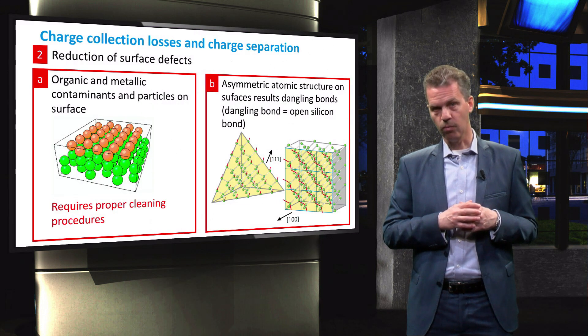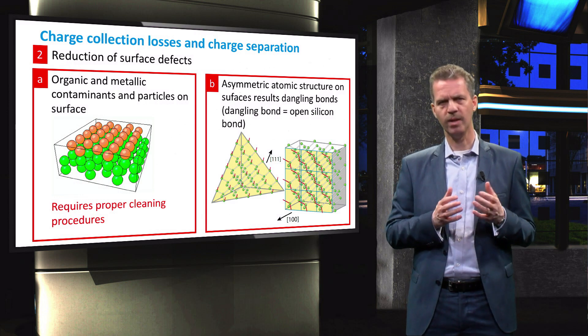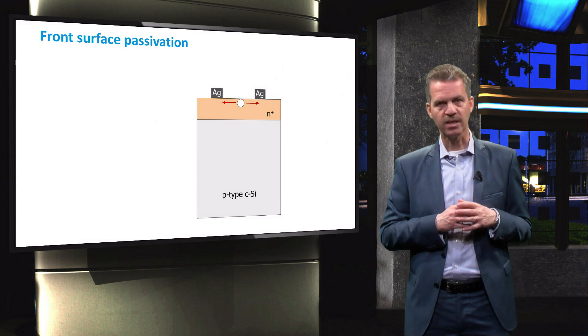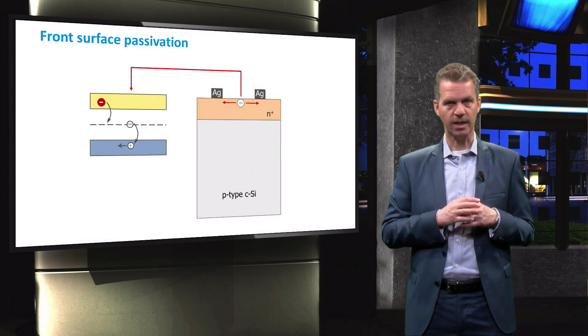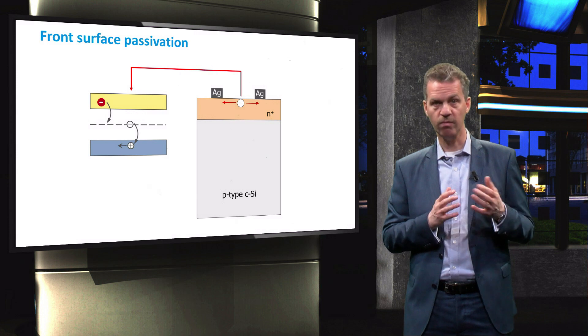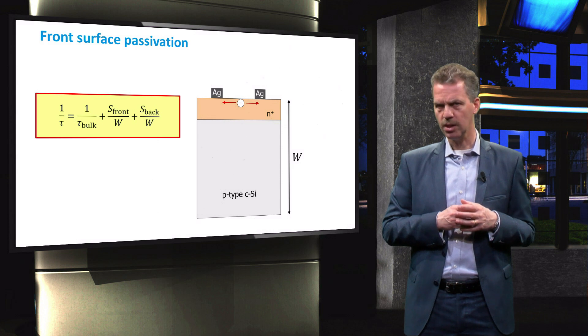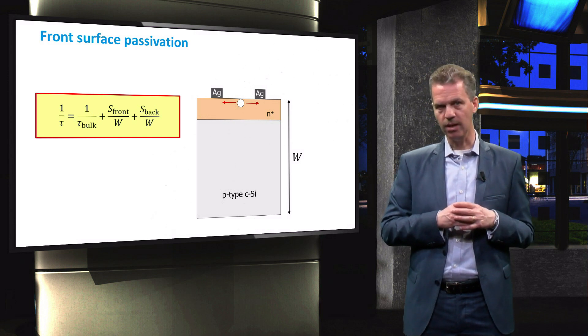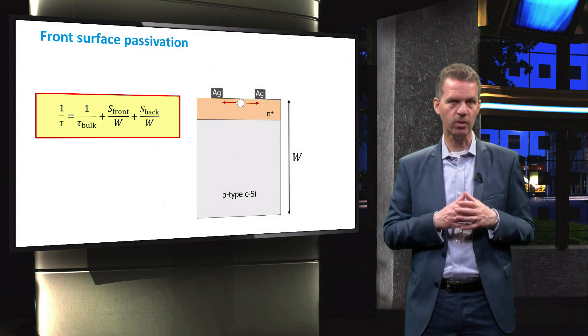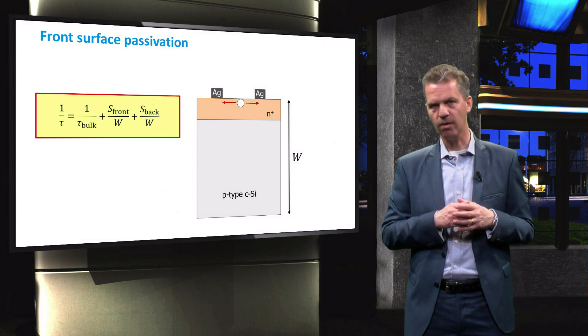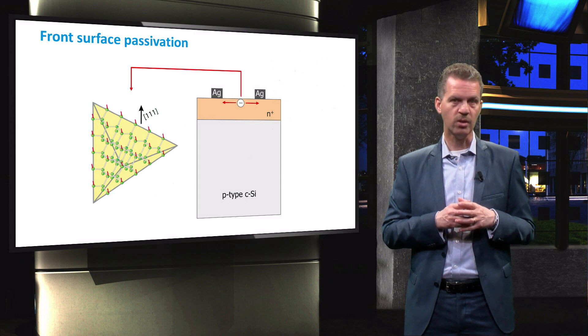Secondly, the surface of the silicon wafer features many dangling bonds due to its asymmetric atomic structure. As an electron moves through the emitter layer towards a metal contact, these dangling bonds act as traps and facilitate recombination. This is SRH recombination, as the trap states at the surface form available energy states within the bandgap of silicon. The total minority carrier lifetime can be expressed with an equation where S_front and S_back represent the surface recombination velocity. The minority carrier lifetime can be increased by reducing the surface recombination velocity, so the density of dangling bonds on the surface should be reduced.